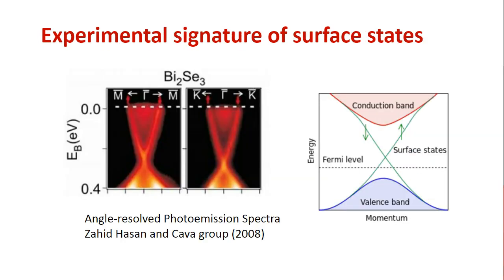None of these hypotheses would be exciting unless it's experimentally proven. So this is experimental data I'm showing on bismuth selenide, and this was only shown in about 2008, as I was mentioning before. Bismuth selenide again is not a new material. This material has been known for a long time. This is actually a popular thermoelectric material. But in 2008, the group of Zahid Hassan and Bob Cava grew the single crystal. Zahid Hassan's group measured this bismuth selenide material using a technique called angle resolved photoemission spectroscopy. And the data is shown here.